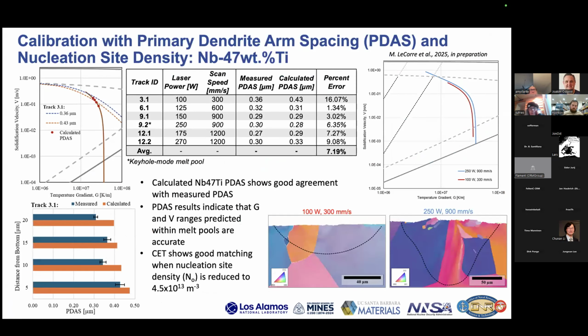She's then going forward and again using other metrics like primary dendrite arm spacing. And this is an example of her comparing calculated PDAS values to actually measured PDAS values, which tends to match pretty well. And then again, trying to better understand the GV conditions we impart relative to columnar to equiax transition. And this is an example for a low power and a high power condition. And we can see for low power, which is actually our trace here in red, we would expect to remain in the columnar regime, where if we go to the high power in this case, we tend to cross over into CET at the top of the melt pool, which indeed we tend to see in this case.